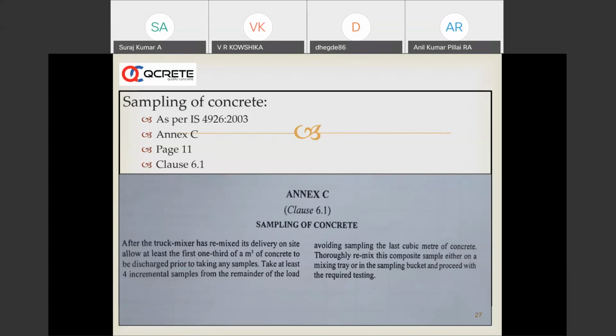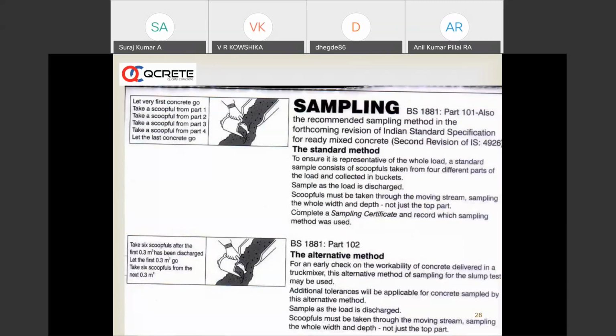There are other codes which clearly speak about the method of sampling. BS 1881 is a very well researched document where they talk about leaving the first one-third of a cubic meter of concrete to go down the chute into the pump or onto the structure, and then you take the concrete sample, running the scoop at right angles to the flow of concrete, in several scoops at regular intervals. It means you have to leave the first part, and you should not take the sample from the last part. In between, at regular intervals, you can take the sample. That is how the sampling has to be done as far as BS 1881 is concerned.